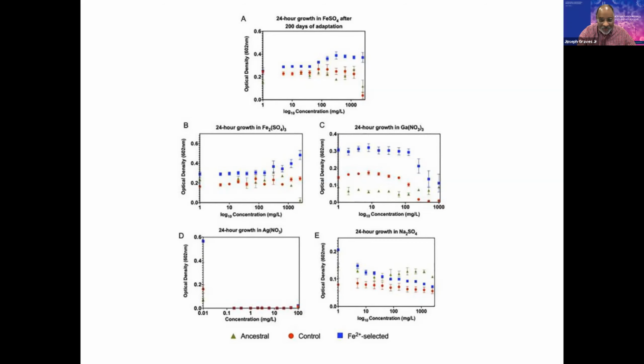Now, to demonstrate that what we were really looking at was a response to iron 2 and not the sulfate ion, we tested 24-hour growth in sulfate, and we found that the ancestor actually does better than both the selected population and the controls, which illustrates that the change that occurred in the controls and in the iron 2 selected population was to iron, not to sulfate.